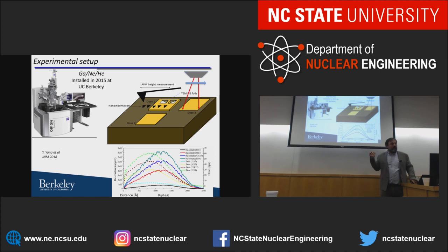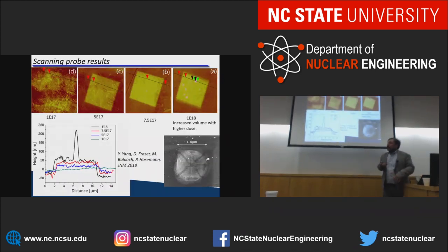Now, what happens if you blow helium into materials? It swells, right? So we blow helium into a surface, in this instance copper, and where we blew it in, the material increases in height. That's an AFM image. Bright means high, dark means low. And what we see is more and more dose, 7.5 times 10 to the 17 ions per square centimeter implantation dose, and 18 and so on. At 18 in copper, we see these nubbles coming up. And it turns out these nubbles look something like that. Interestingly, they have these black X-shaped things, which I'm going to come back to later. You measure the height increase as a function of dose and get your swelling parameter out of that within about 3 hours' worth of work.